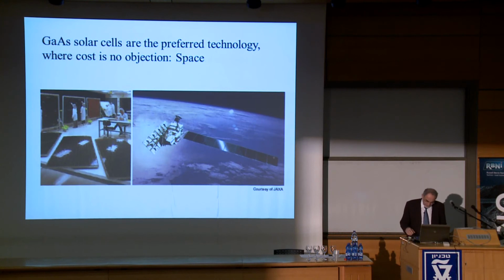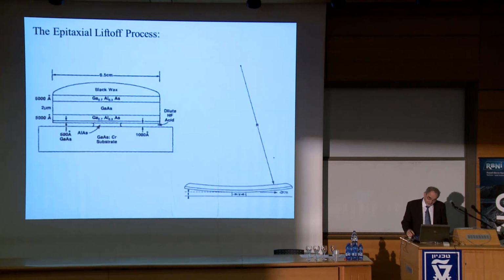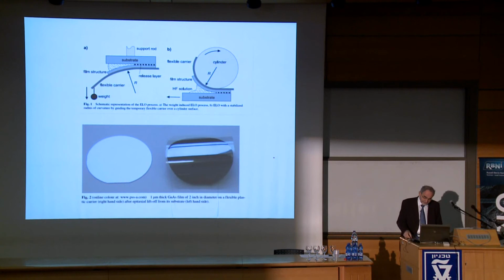Well, here's one more slide I want to show. No one questions that gallium arsenide is the best, because where cost is no objection, gallium arsenide solar cells are used. For example, in space, they don't worry about the cost, and so they are the highest performing solar cell. However, it is possible to reduce the cost. And the way to reduce the cost, this is an old paper I wrote, and you have aluminum arsenide and you bring in acid and you peel the film, and you can peel the film over a big area. Let me show you another slide of peeling the film. This is from Netherlands, but they do something very similar. You have a droplet of acid, it goes in, it undercuts the film, and you peel it. The one up on the screen is only 2 inches.